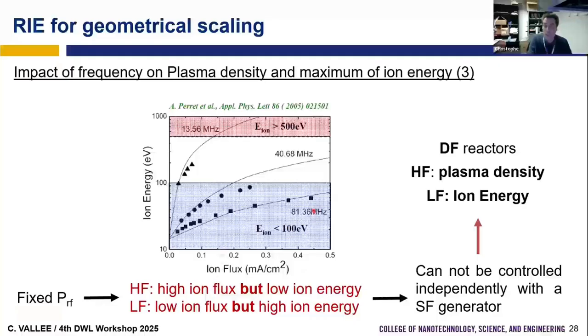But since we have very high ion flux, the current flowing to the substrate is high. So for the same power, since we have more current, we develop less RF voltage, or less peak to peak. And if we develop less peak to peak, we develop less DC bias. So the ion energy is low. So with a high frequency generator, we may have high ion flux, but low energy.